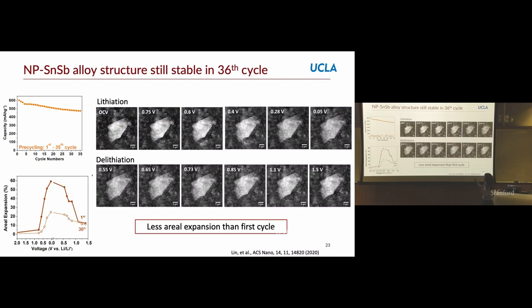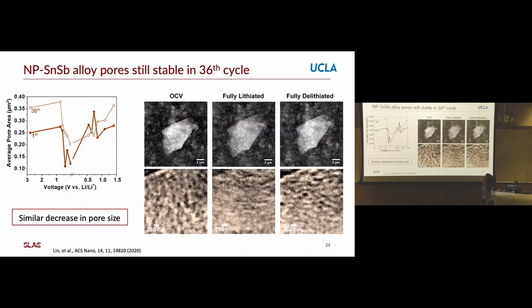And it's actually probably going back to sort of the normal amount. So it's always slightly less expanding than the first one. So less expansion than the first cycle, but it's still being able to expand and contract without cracking. And so really being able to have a cell that you can put into a microscope that is working like a real cell in a lab, where it cycles for hundreds of cycles, is really important if you want to not just study the first cycle.